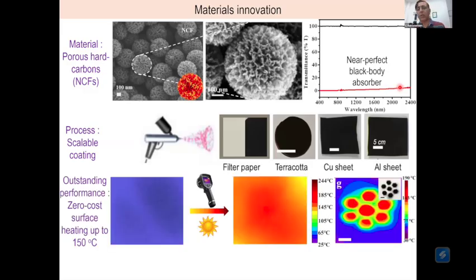The next question is, what happens to this energy? Because when it absorbs photons, it means that it absorbs the energy from the light photons. So for that, we looked at thermal imaging, thermometric imaging, to try to measure the surface temperature. For example, this is the surface which is put in the dark. The minute we put it in sunlight, you see that the surface temperature shoots up, as shown in this red image, and it reaches almost up to 150 degrees. This is just clean green heat that we are generating on the surface just by putting the coating in sunlight. The material absorbs the sunlight and converts it to heat. So there is this photon to phonon conversion, and the phonon gets manifested as heat energy at the surface of this coating.